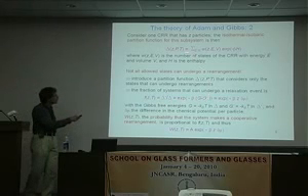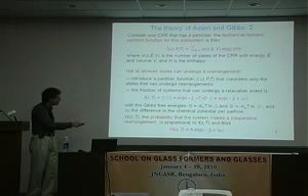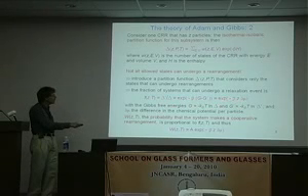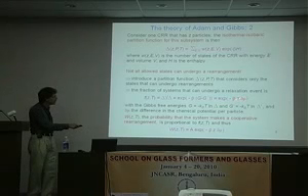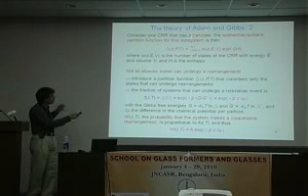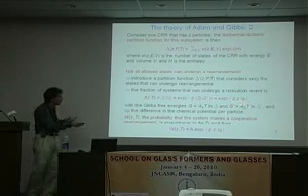And if you plug in the Δ and Δ prime, and you use the Gibbs free energy as definition, then you get out this expression here, and you can express this ratio here as an exponential of minus beta z Δμ. z is the number of particles in your region, which is considered as fixed for the moment. And Δμ, you should just see this equation here as a definition. This equation is the definition of Δμ. That is to say, it's the chemical potential per particle.